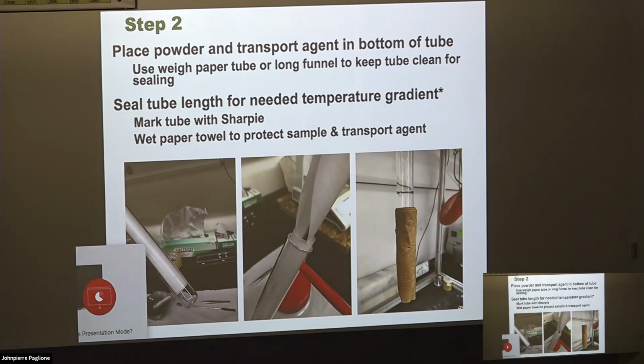And start the vapor transport. So one trick she has, essentially, when you're putting powder in a tube, you don't want the powder to coat the sides of the tube. It makes it hard to seal the tube properly if there's any kind of powder on the side. So you can use a weighing paper or something to make a little funnel for your powder, so your powder can get to the bottom of the tube without coating the side. That makes sense. So that's a nice trick.